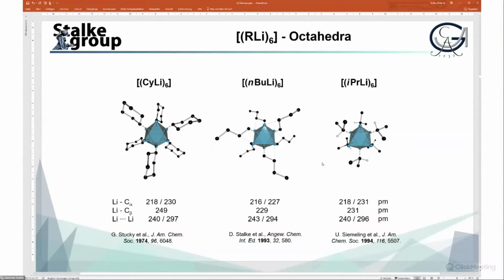A couple of years later, from Ulrich Siemeling, we had isopropyllithium with the same pattern. What you see from the structures is that the lithium C-alpha distances are not much shorter than the C-beta distances. Look at this, there is only 2 picometers of difference, and they are similar in isopropyllithium.